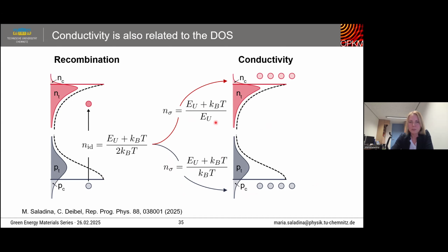different. And if you relate the two ideality factors, the recombination to transport, for the same charge carrier, you always get 1/2. But if you have opposite dominance, then this dependence will be different. So essentially it will be ideality factor minus 1/2.